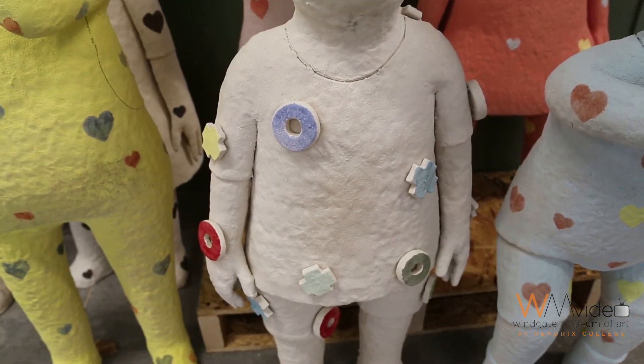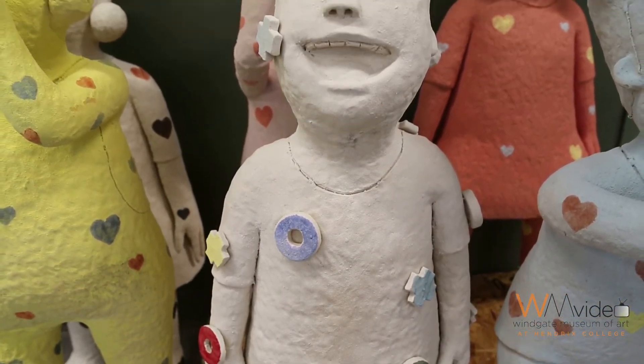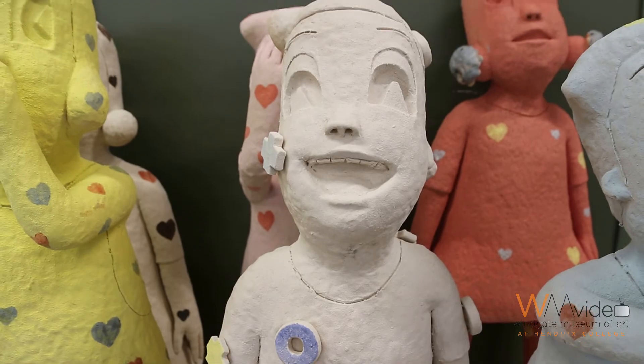I make a lot of pieces and I practice my hands a lot, to see if 'me' appears. It's like handwriting. My clay stoneware, which is high temperature clay, is supposed to fire up to 2,300–2,400 degrees. But I fire to 1,945 degrees, which is in the low fire range. That way I can add colors over and over, refire my piece as many times as I want, and keep developing the surface and texture.